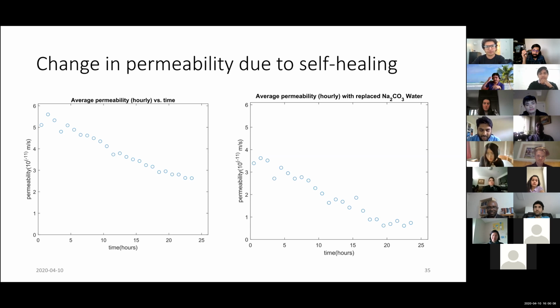Do you know what the solubility of sodium carbonate is? I just wanted to saturate the water itself. The solubility is around, I think, 9 grams per 100 ml or around that region. So it's slightly higher than the solubility. In the pond of sodium carbonate you were using, were you trying to agitate it continuously, or did you observe any precipitation in the pond itself? Once I dissolve it, I don't observe any precipitation in 1 or 2 hours.